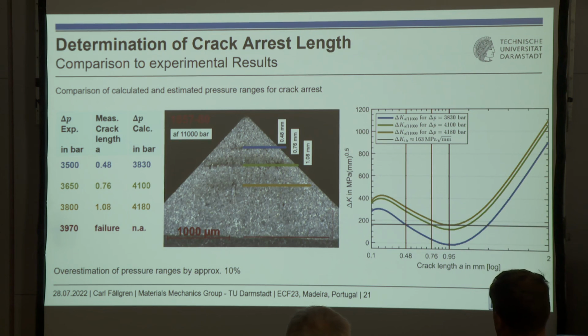So in the figure in the middle, you see the failure origin, and you see arrest lines of cracks that we managed to get from the experimental approach that we used. One minute to finish, please. And on the right side, you see our linear elastic fracture mechanics approach. And if you compare,